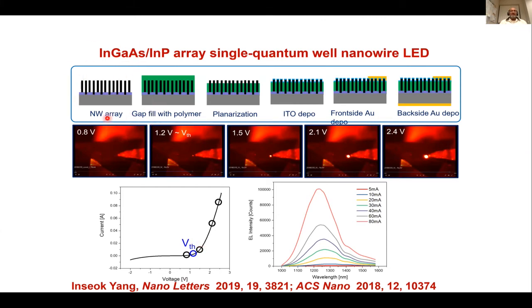array LED. For example, these nanowires are grown vertically. You fill these nanowires with a polymer material and selectively etch those ones and put some indium tin oxide and some metal on the top and the bottom. And again, you inject the current or apply the voltage and measure the current or IV characteristics. And again, here more and more current is injected and more light is coming out of these ones. You can see, in fact, the bright light coming below the probe here, indicating that he has been successful in being able to make quantum well nanowire LEDs.